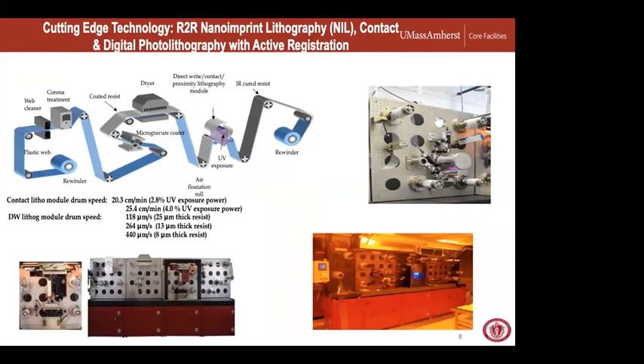In addition to the cutting edge side of things, so not only is the nanoimprint lithography fairly cutting edge, but we've also got a contact lithography. Again, this will coat a photoresist and pre-bake it. It will then align that to a photomask, which is wrapped around a drum with a UV exposure source inside it. And then as it rolls past that, you get a pattern formed in the resist where the UV light is allowed through. Basically, this allows us to create these patterns, and you might do something subsequently like either an etch or a deposition to create a metal pattern or some other pattern on that substrate. Ideally, what we would do then is come back through and align another pattern over that. That's the advantage of this.